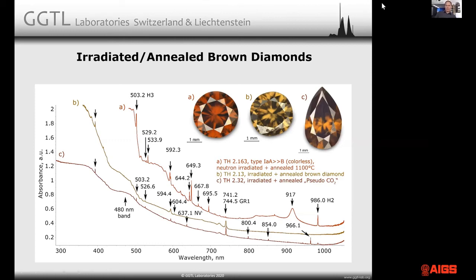But if you irradiate the stone heavily, you will always keep a continuum. And this continuum is from a defect that must be very similar to a vacancy cluster. It's an accumulation of many vacancies that's relatively stable to high temperature treatment. This continuum will only anneal out at about 1750 degrees. So the stone stays basically the same color until you go above 1500 at least, and then you start seeing the continuum disappear. So it's a highly stable vacancy-related defect as well.